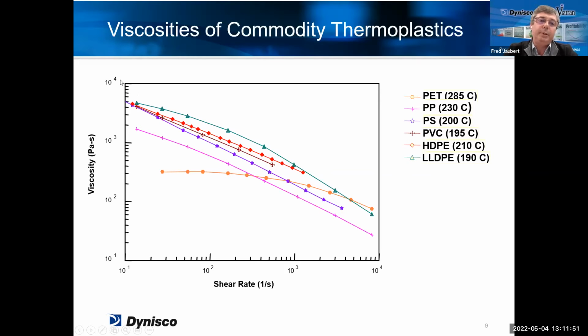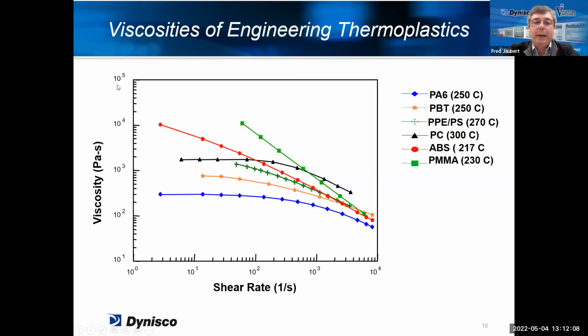If I show you this, it's just so that you can see the magnitude of the viscosity we have on the commodity resins and the shear rates we are generating compared to what we get with what we call more engineering resins. Here we are at 1,000 Pascal seconds, while when you are running the same type of testing on more engineering thermoplastics, you see that we are going a little higher. And in fact, we need to extrapolate this curve, so we have much higher viscosities in this product than what we get with more commodity resins.